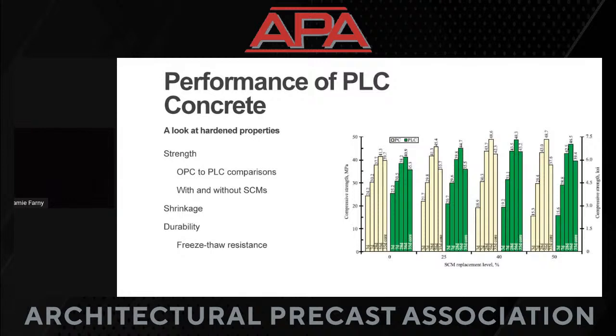So this is telling us we get the same ultimate strength with a PLC mix. We also get the same strength development with a PLC mix. So we figured out compressive strength. You can do it with or without supplementary cementing materials. If you need those for either a durability aspect or to bring down your carbon footprint because you have fly ash or slag cement that doesn't have the same CO2 footprint as cement, they work well together. That's the bottom line message there.